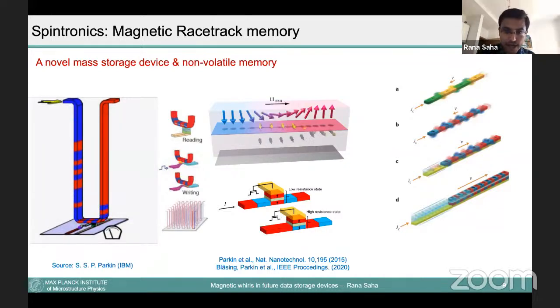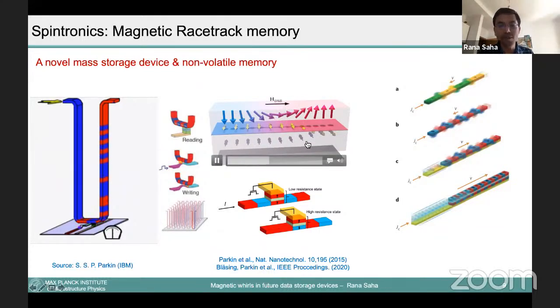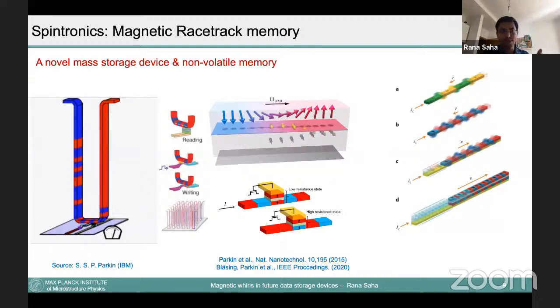This is a magnetic metal on top of a heavy metal, and at the interface you have a spin polarized current. This spin polarized current applies some torque, and because of that the domain walls which you see on your left side move from left to right or right to left. In this way you can move the domain wall back and forth, and you can move your data.